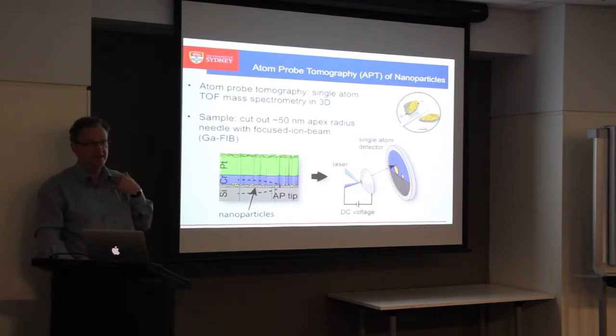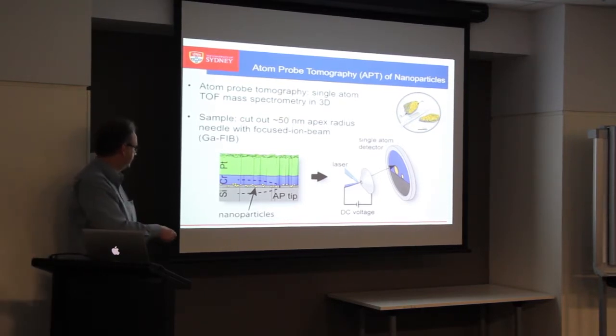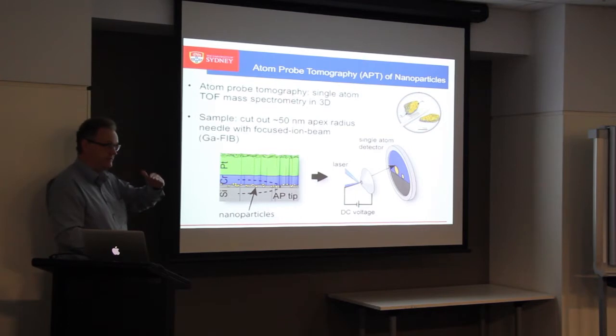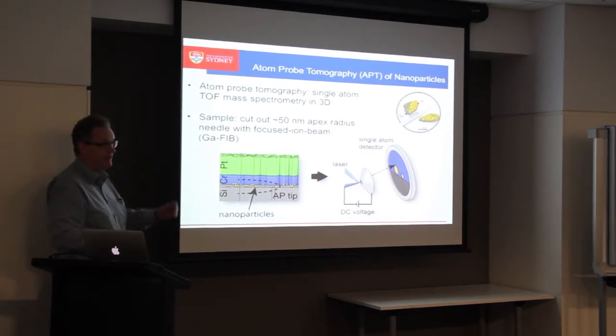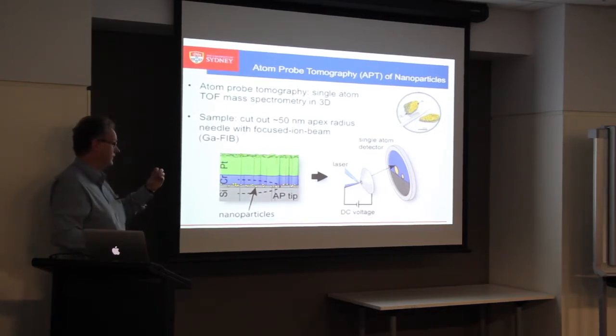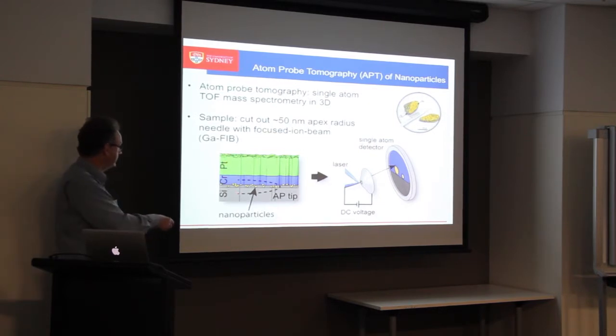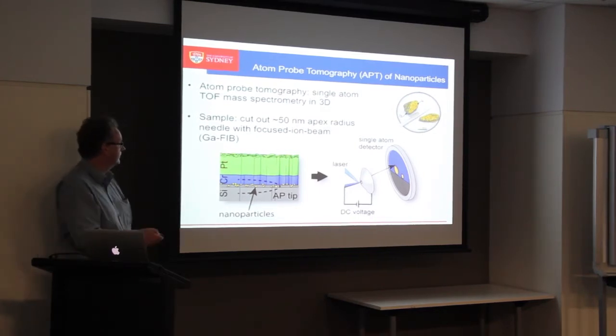Our contribution is that we've achieved real atomic resolution for this system. The way we did it is we had a silicon wafer onto which we put the particles. We put a layer of chromium on there, and then a layer of platinum. Platinum is what people normally use. Our invention — after much thinking — was that chromium should allow us to compensate very well for all of these issues of thermal expansion, vibration, and charging effects, whereas silicon and platinum are just a little bit too different from each other.